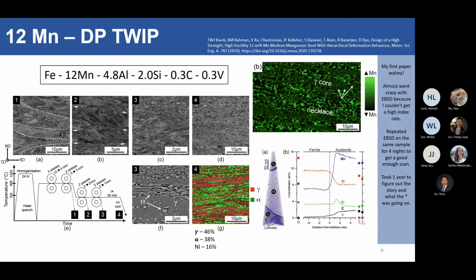For this steel, what we did was that we warm rolled it at 700 degrees here. So 700 degrees is within your two-phase region. And what it does to the microstructure is that it elongates your austenite grain. And with every pass, you add something called a necklace layer around it. So the necklace layer is this layer of very fine austenite and ferrite grains, because you don't have enough energy to cause a full recrystallization. So it only recrystallizes on the outside. And with every pass, you add a layer, you add a layer, you add a layer, until finally you have some microstructure that looks like this. So you have a very highly deformed austenite core surrounded by necklaces of very fine ferrite and austenite grains.